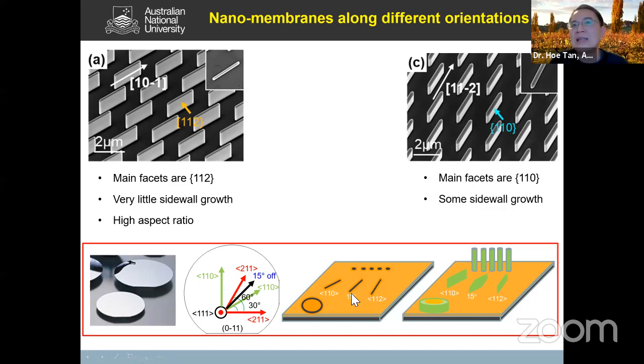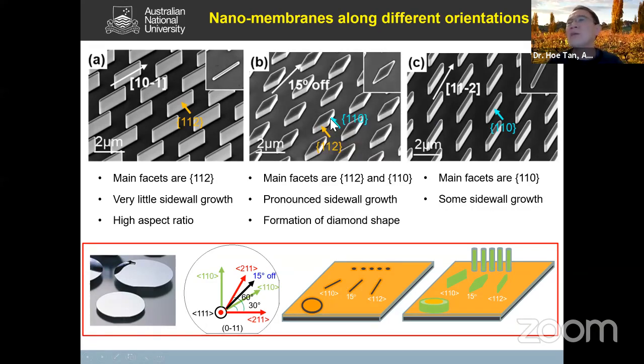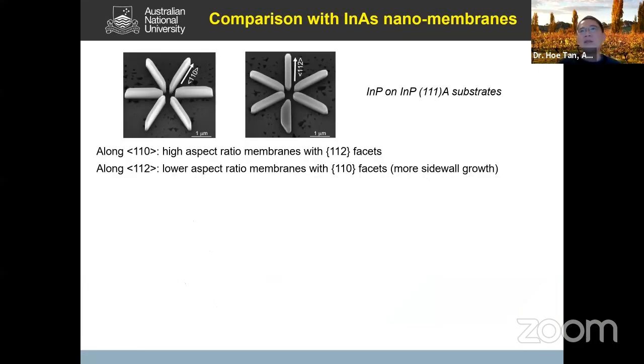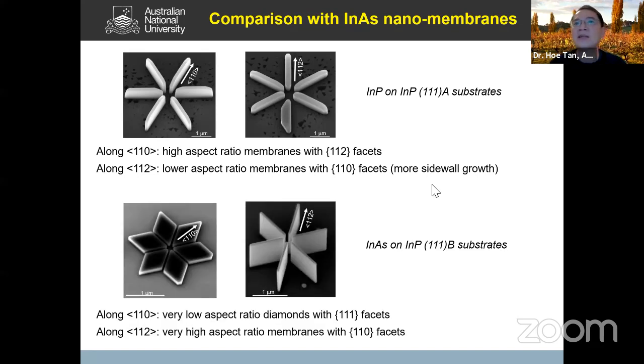What happens now if we align this line somewhere in between these two orientations? As you can see here, now it forms more like a pyramidal prism kind of structure, and this facet is bounded by a combination of those two facets. So that is very interesting. As I've shown you, whether you align it along 110 or 112 for indium phosphide, you get essentially nanomembranes, just that the width is slightly different. But if you do the same thing for a different semiconductor, for example indium arsenide, then if you align it to the 110 direction, instead of forming a membrane, you form more like a nanoprism. And if you align it in a 112 direction, it forms a very narrow one, much narrower than these two.